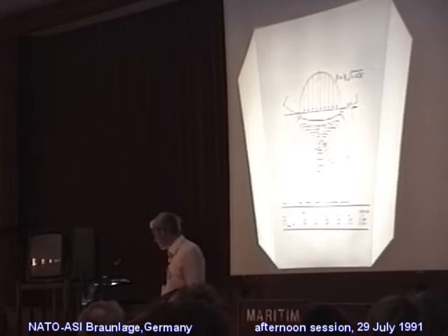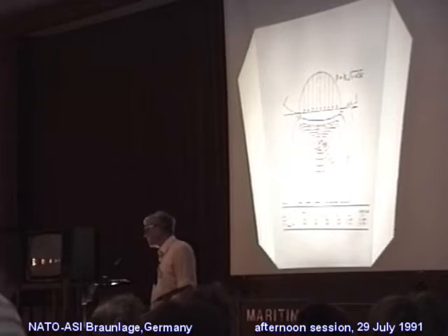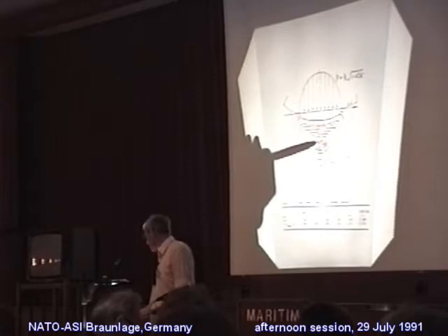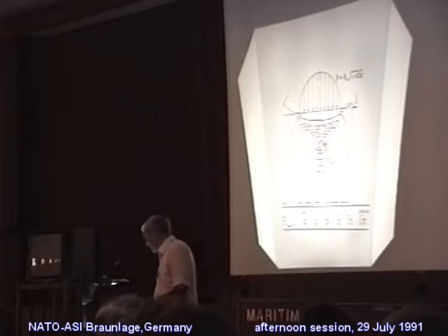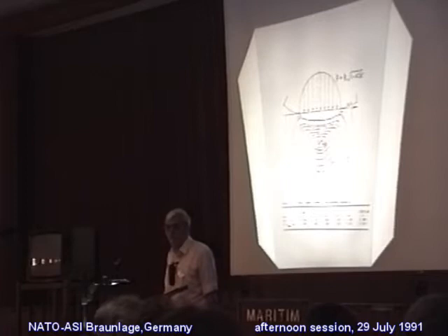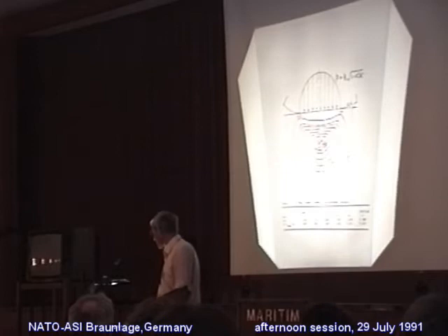In Hertz's second paper, he actually said his theory would give a logical basis for hardness measurements, because he would know about this point of initial yielding, which was going to be his measure of hardness. That's about the only thing in Hertz's two papers which hasn't lasted to the present day, and which wasn't absolutely top class from the beginning, because you can't detect that yielding by observations of the surface, which makes that proposal unworkable.